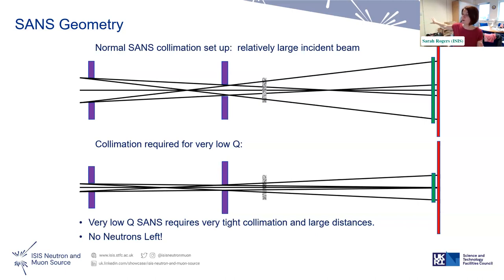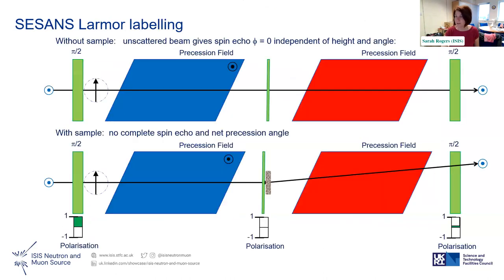And basically, if you keep going, you'll have no neutrons left because the pinhole gets smaller and smaller, the detectors get further away, you have no scattering. So to try and get over this problem, the guys have developed, and this is a big collaboration with TU Delft in the Netherlands, a technique called spin echo SANS. So this is Larmor labeling.